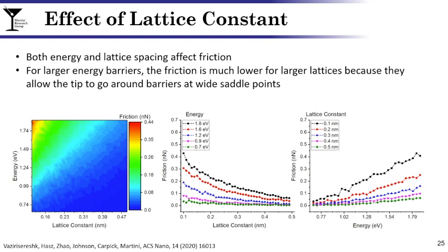But the more interesting plot perhaps is the one in the middle, where we see friction as a function of lattice spacing. What this tells us is for materials that have similar energetics as for our three TMDs, friction will go down with lattice constant. And now we know this is because it allows the tip to more easily move through these wider saddle points.